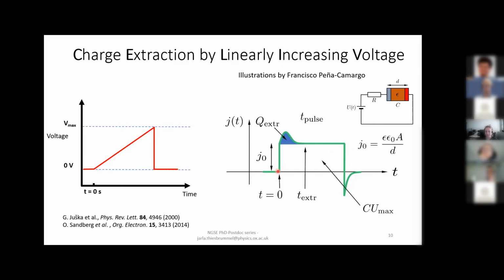But the interesting thing is that if there are other charges present in the system, you can also see them in the CELIV measurement, but only if they are at significant concentrations compared to the capacitive charge. So if you have a significant concentration of doping, then you see an additional bump on top of the capacitive charge. And same for the ions, but then of course at much slower timescales. If we have a significant concentration of mobile ions in the system that are moving around, then we would again get a bump on top of the capacitive charge.